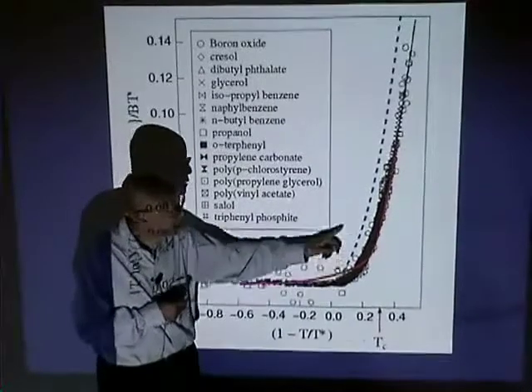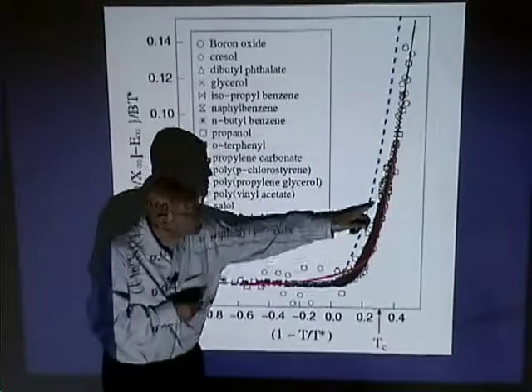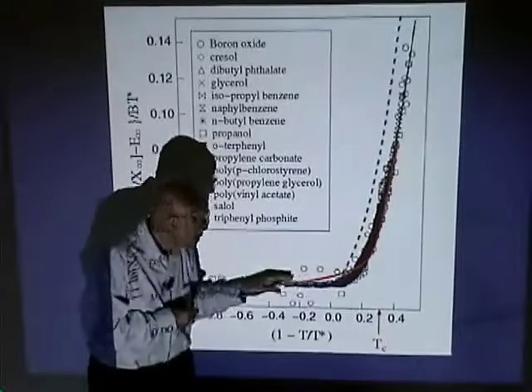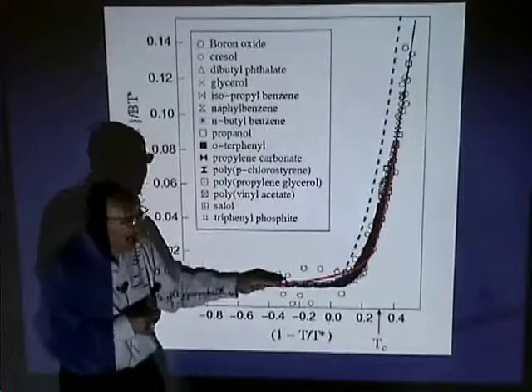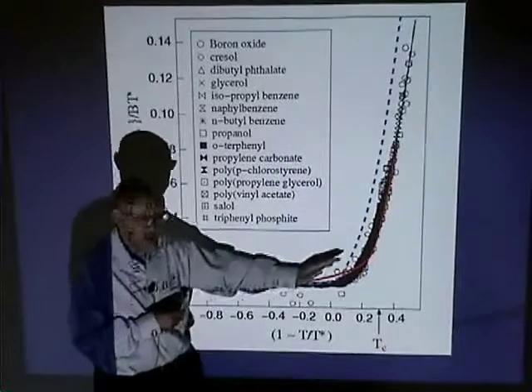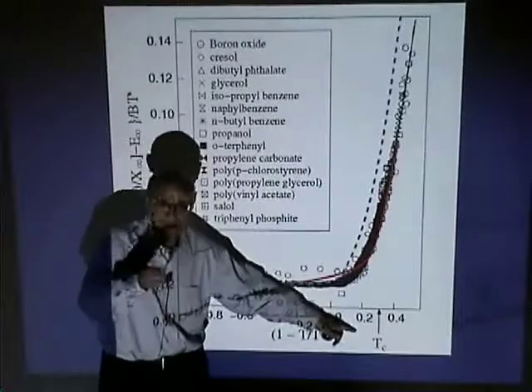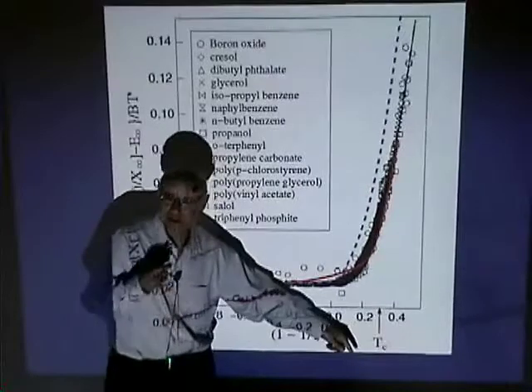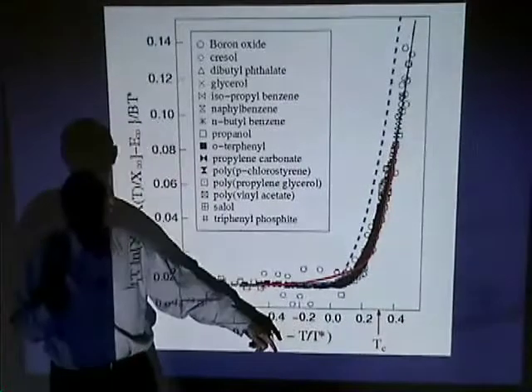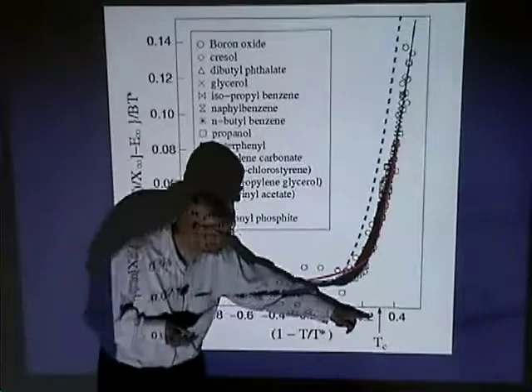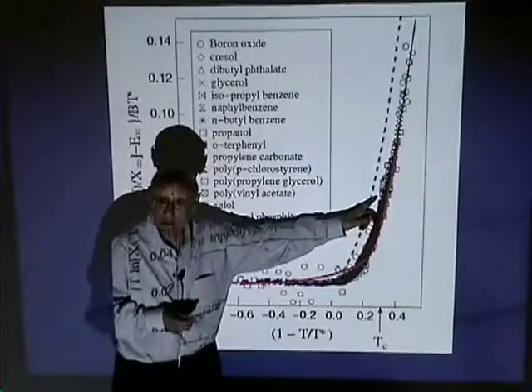Notice that the heuristic curve indeed overestimates in comparison. It shows this plateau at high temperature, and then it has a steep rise. By the way, for the binary Lennard-Jones, we know what the MCT temperature is, 0.43 or so. That's right here, so it's right near the knee.